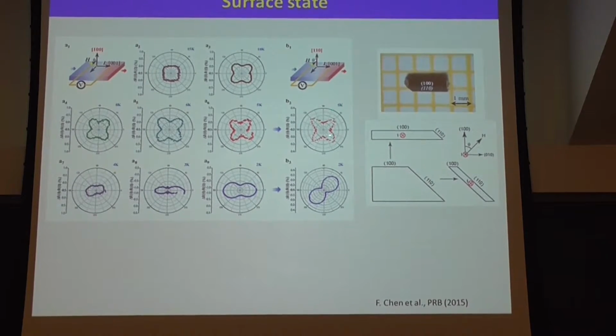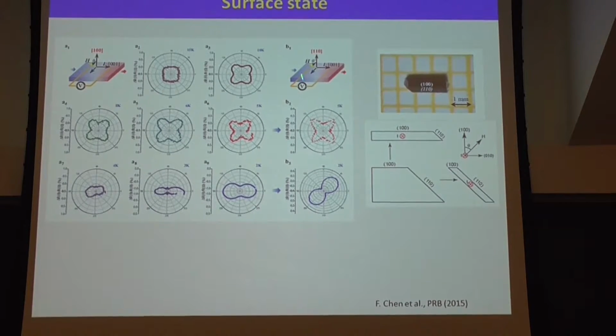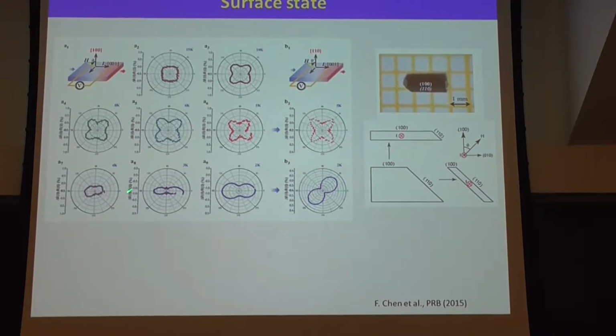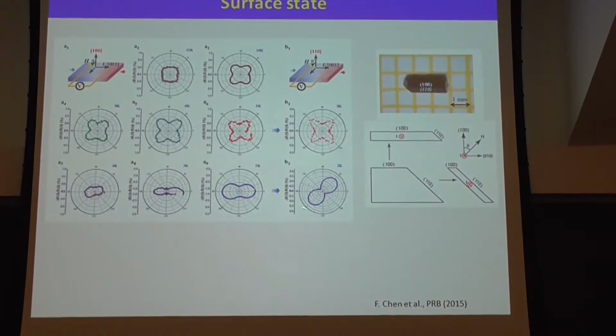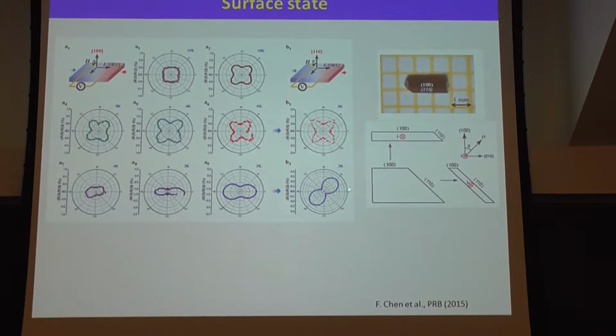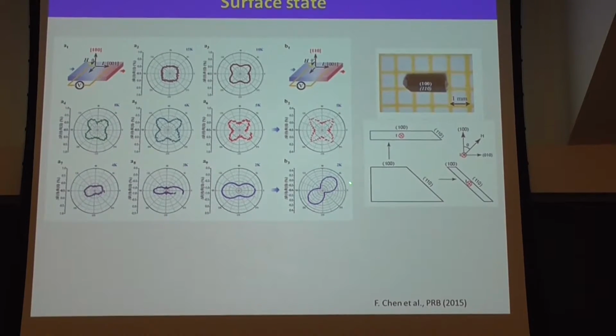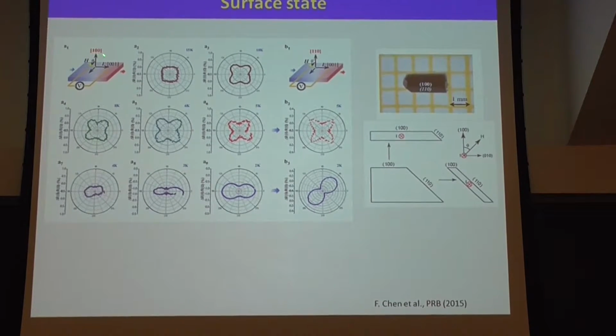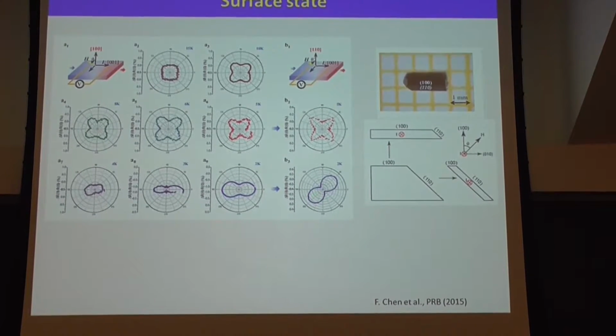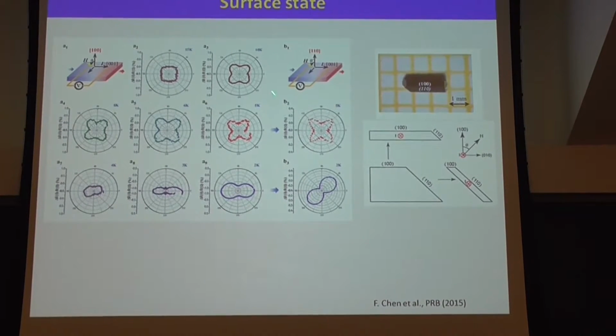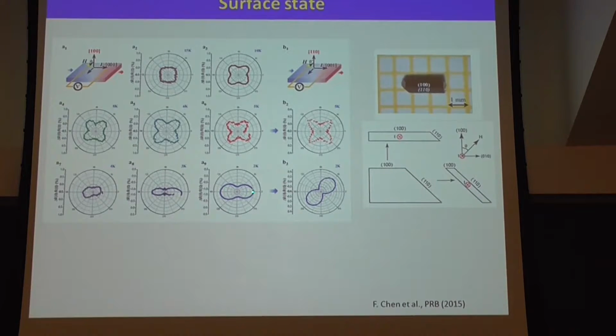But above 5 Kelvin it is also fourfold symmetry. For this surface and this surface it is exactly the same. But below 4 Kelvin, the anisotropy, the surface symmetry, changes to twofold. But also you can see that between the 100 surface and the 110 surface, the phase is shifted 45 degrees. From fourfold to twofold is easy to understand because